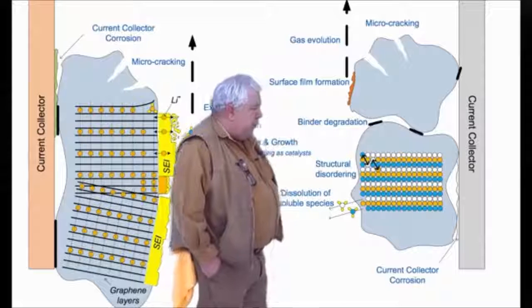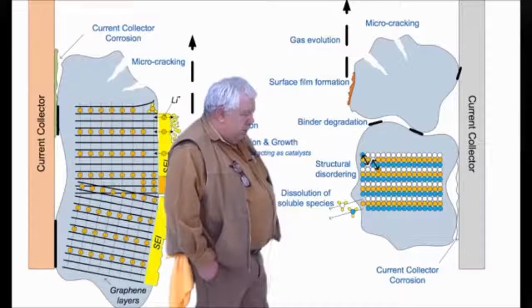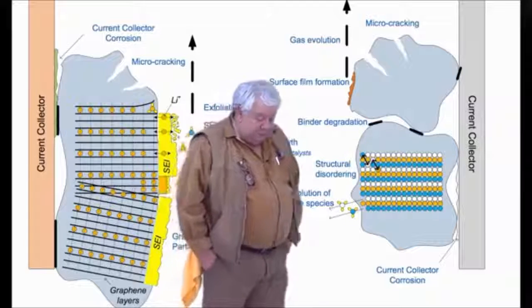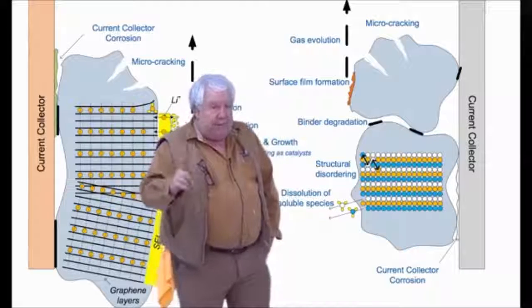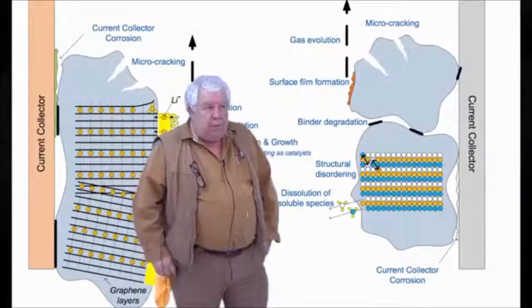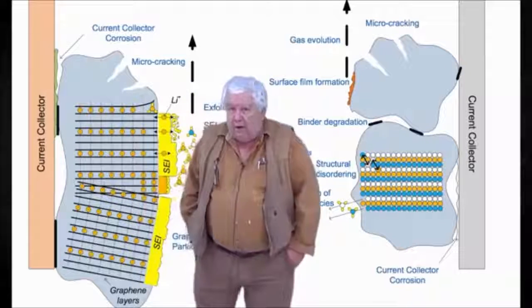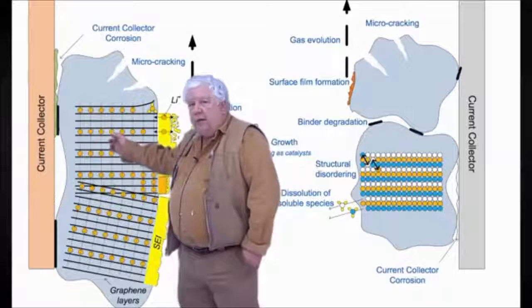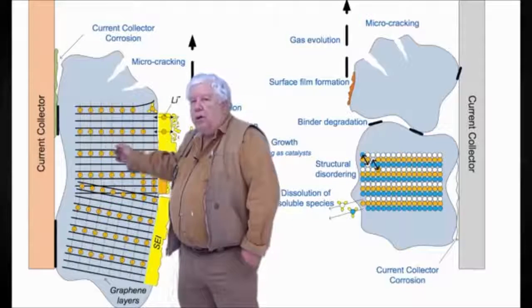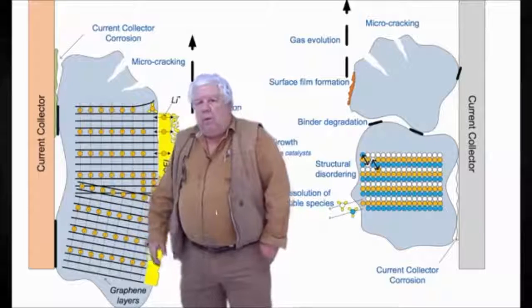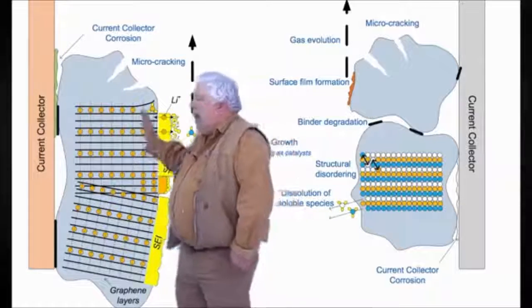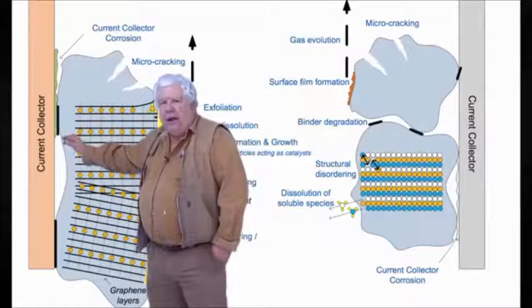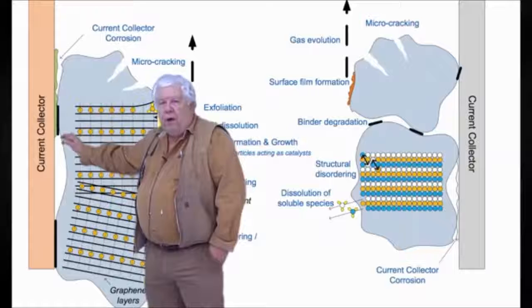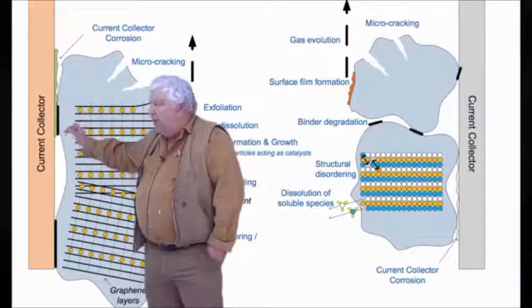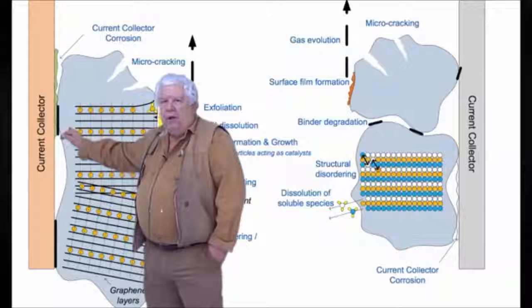So that's your two failure modes: over-discharge and overcharge. And overcharge is the more likely to cause a fire. Over-discharge can as well, if a dendrite pierces the insulator and shorts to the next cell, you will get current flow and it will cause heat. Well, now we've got the same problem. That heat is going to break down the SEI layer and melt it. And again, between 110 and 130 degrees centigrade, this comes apart. It doesn't care where the 110 or 130 come from, it's still going to come apart and go into thermal